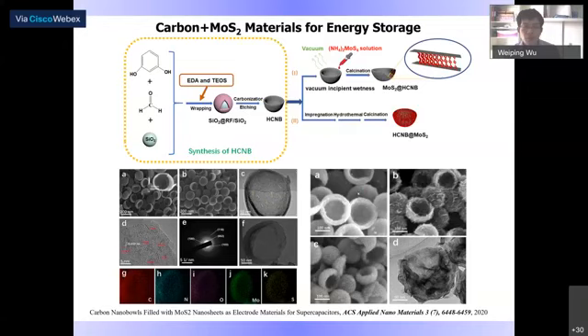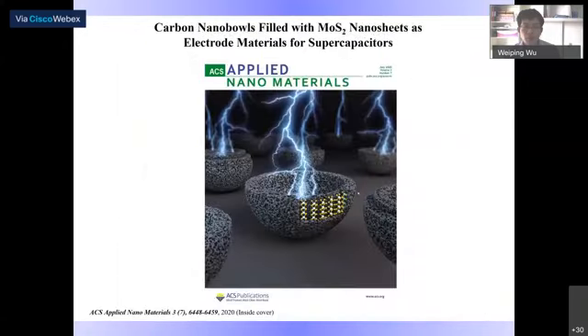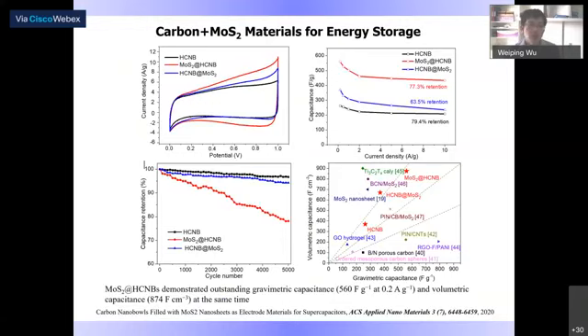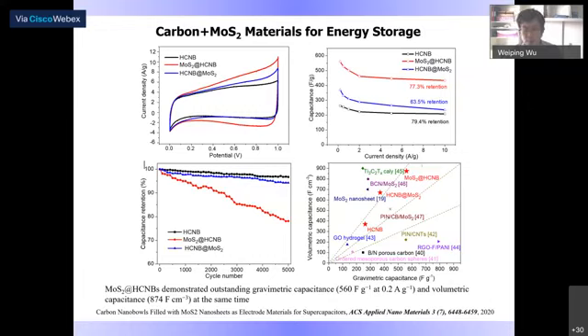So by comparing the chemistry and energy storage performance, the supercapacitor performance, we actually have made a breakthrough in this area, by achieving gravimetric capacitance and volumetric capacitance at the same time. As you can see from the last chart of this slide, compared to the state of the art of emerging materials for supercapacitors, we balance these two performances and reached one of the best performances among various reported results.